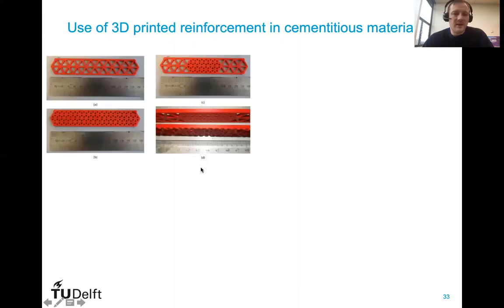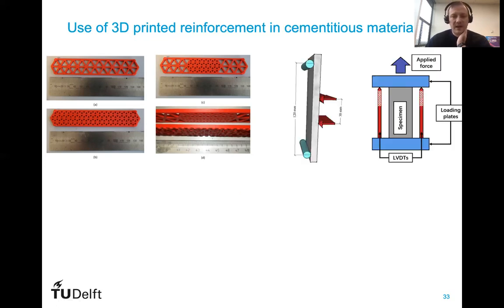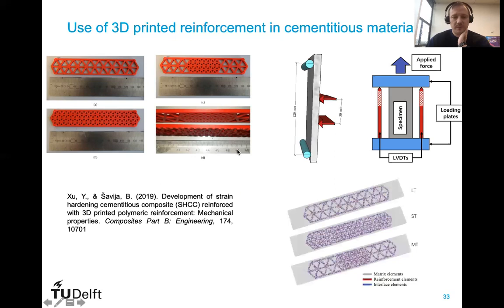So what we did, we designed several very simple meshes in triangular shapes. So we have what we call large triangles, mixed triangles, small triangles. And with 3D printing, you can also influence the roughness of the mesh. So you can build in edges similar to ribbed bar reinforcement to increase the bonding between the reinforcement and the matrix. And then we cast these into mortar bars and tested them in 4-point bending, in flexure, and in uniaxial tension. And because the presentation is about the use of models, we have also created modeling representations within the Lattice modeling framework of all these three different experiments.